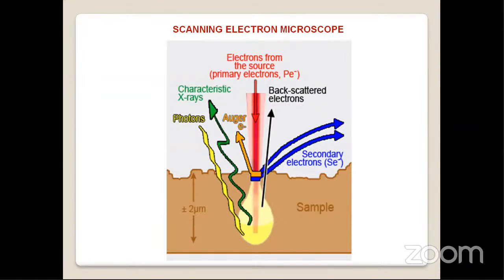Then backscattered electron. This is related to the elastic collision. It won't give any information by itself, it is simply backscattering. But this backscattering will provide information about the elements along with the characteristic X-ray. Characteristic X-ray and backscattered electrons will provide the EDX, energy dispersive X-ray spectrum analysis. What are all the molecules present in the sample? All that information one can identify.